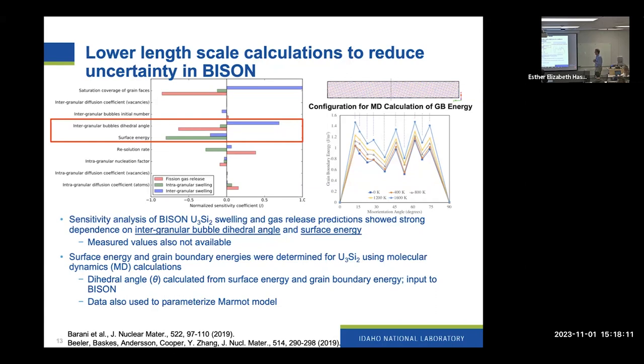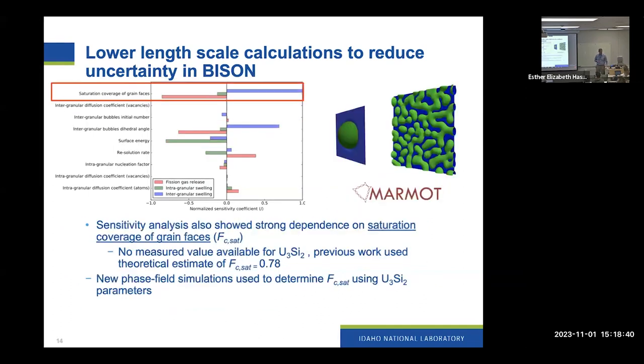So my former colleague Ben Beeler developed an interatomic potential for U3Si2 and used that to calculate the dihedral angle based on the surface energy and grain boundary energies, which can be calculated from these MD simulations such as shown here. And then he was able to pass that into Bison, but we also needed to know another parameter in the model, which actually was even more important, which is the saturation coverage of grain faces.